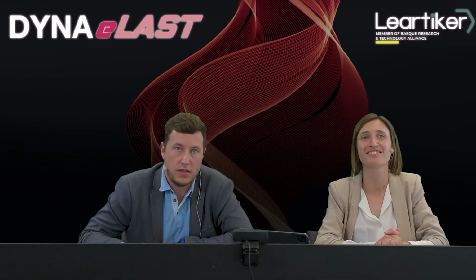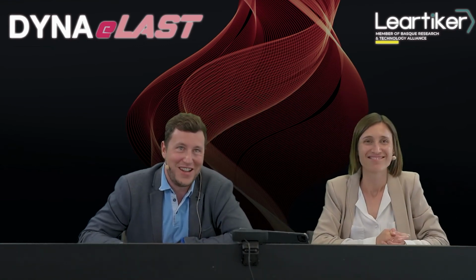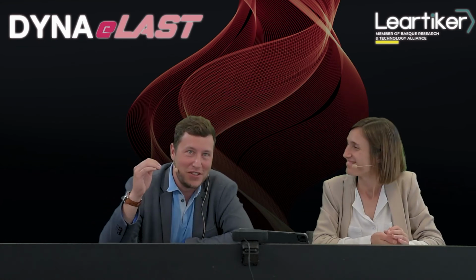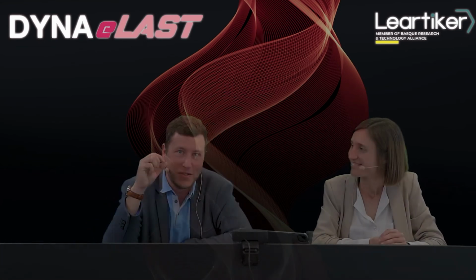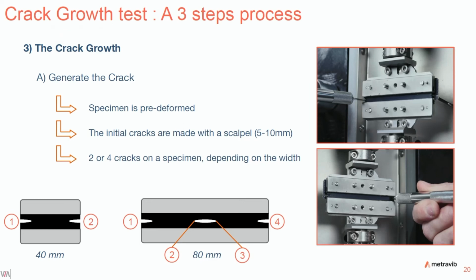And finally, the last step is to generate the crack. First of all, the specimen is pre-deformed, and you can make an initial crack with a scalpel, generally with a length of 5 or 10 millimeters. Depending on the width of your specimen, you can cut 2 cracks or 4 cracks with 80 millimeters. So you can follow, with this kind of specimen, 4 cracks at the same time with the system.